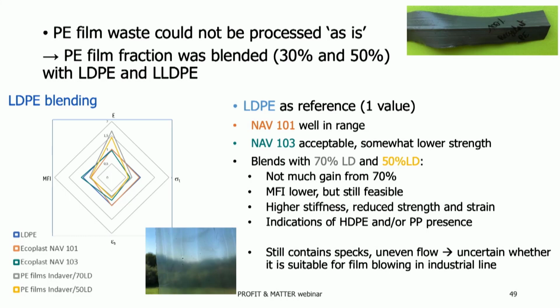If you look at LDPE as a reference, we see that the blends with polyethylene recyclate have a lower MFI, but were well processable on lab scale. Also a higher stiffness, but reduced strength and elongation at break were remarked, and this can be caused by the contaminants that are present in this waste stream.